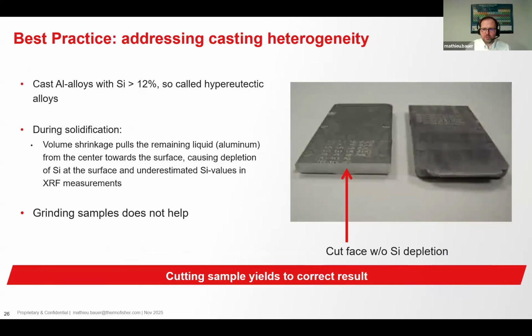Then a further interesting case is actually the analysis of cast aluminum with silicon content being higher than 12%, that are so-called hypereutectic alloys. And so during the solidification of the melt, there is a volume shrinkage that pulls the remaining liquid, in this case aluminum, from the center of the material toward the surface. And this causes actually a depletion of silicon at the surface, which itself causes readings being 1 to 2% lower for silicon. So that means about a relative 10 to 20% underestimation of the silicon content.